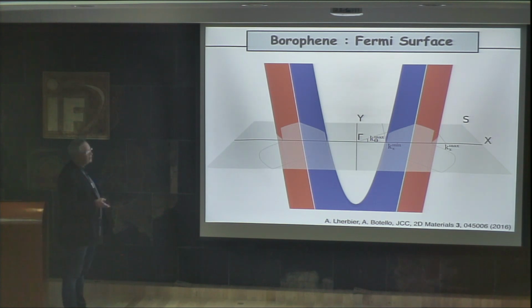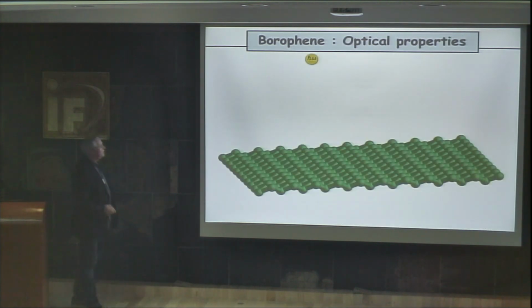So this is the Fermi surface. The Fermi surface of a 2D material is just a 2D line, in fact. And this is the 2D line of the Fermi surface. So you have a clear k vector which will induce transport along the kx direction, but you will not have it along the ky direction. So you have a kind of threshold angle with the maximum, with a kmax value, which is here, in fact, which goes to this point between Y and S, which allows transport. The transport will be clearly anisotropic in this system.